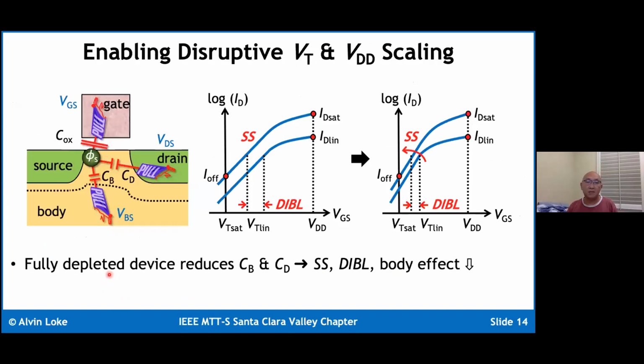Okay, so what does a fully depleted device offer you? Well, by having the dopants be a lot less, you can have marked reduction in the body and the drain capacitance, which means that this tug of war is now strongly favoring the COX. And so what that means is that every millivolt of gate voltage change you have will have a much larger percentage of that millivolt show up as a change in the surface potential. The net result is you need less gate voltage to change the subthreshold current by, say, three orders of magnitude, for instance. And what that means is that the subthreshold slope gets steeper.